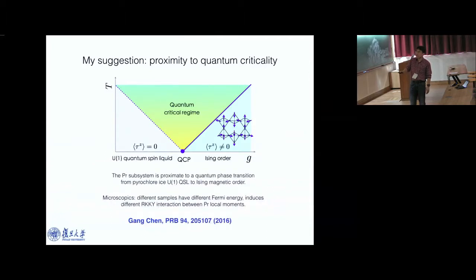As I said, the proximate magnetic order observed by neutron diffraction in this material is the 2-in-2-out spin ice order. And the metamagnetic transition indicates there is Ising spin anisotropy. So a natural guess is that this proximate disordered state is going to be a U(1) quantum spin liquid of spin ice type. If one assumes that, one can study the instability of this state and ask whether one can predict the right-hand side: by studying the instability of this U(1) liquid, can one produce the right magnetic order that has been observed in this system? This is the work I did by myself in this long paper.